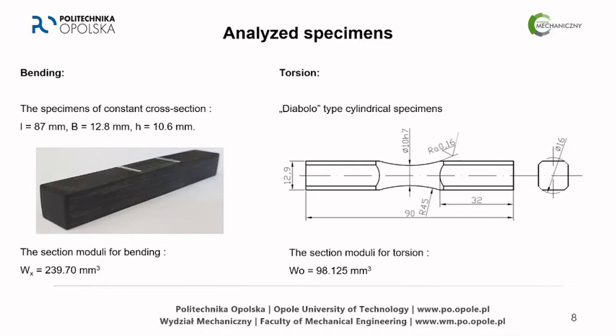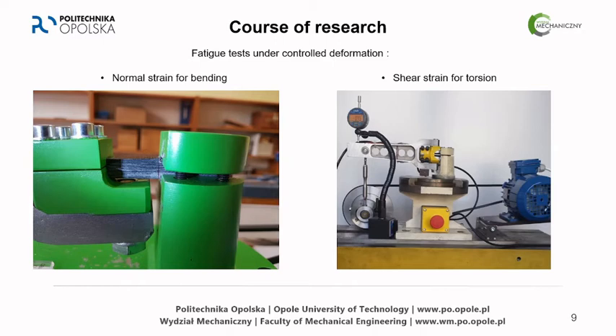The specimens which we were taking into account are two types. For bending, we had specimens of constant cross-section, and here we have for torsion the Diabolo specimens, which scheme you can see on the right of this page. These are typical specimens which were used in our tests. And here you can also see the fatigue test. It's worth saying that we use the controlled deformation in both examples. And on the left you can see the photo of a specimen during bending, and on the right you have it for torsion.